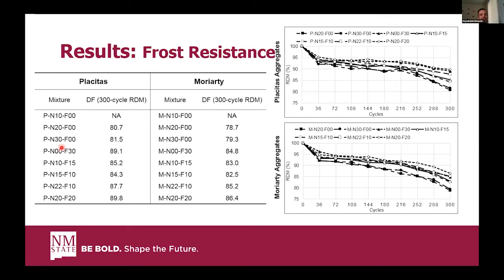For the frost resistance test, we found that the durability factor, which is the relative dynamic modulus after 300 cycles of freezing and thawing, was more than 78.7 for all mixtures for both aggregates. But the important point here is that the durability factor of mixtures with 30% fly ash was slightly more than the mixtures with 30% natural pozzolan, which suggests that when we're going to use this natural pozzolan in an area where frost resistance is important, we should be careful. But the good news here is that most of them are acceptable because they are more than maybe 80, so we can use them anyway.